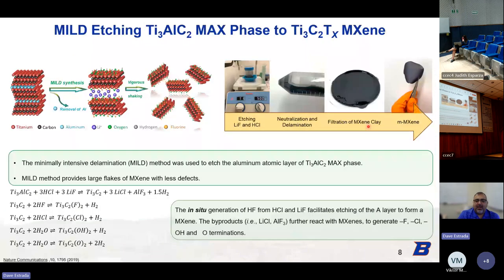Once we have the MAX phase ceramic, to get to the MXene we actually have to remove that A element. We do that, following Yury Gogotsi's work, through the MILD method, where we generate in situ HF through lithium chloride and/or lithium fluoride and hydrochloric acid. That reaction will create HF, which can selectively remove the aluminum layer in a Ti3AlC2 MAX phase, for example. We let that reaction occur for about a week and we monitor the pH over that time to understand when the reaction is complete. Then we do a lot of XRD analysis to ensure that these things are fully etched and we have the MXene layers. You can see that here on this plot.